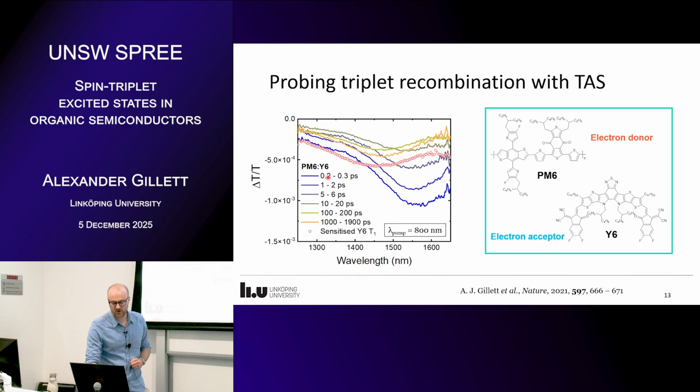What we find is that with time, as we go from blue through these beigey, green, yellow colors, we see a quenching of the absorption band at 1550 nanometers, and it goes away. That's just due to hole transfer from this molecule to the polymer, basically quenching the excitons. And indeed, there's a polaronic absorption of this polymer. I'm not showing it, but it's somewhere down here at about 950 nanometers or so.